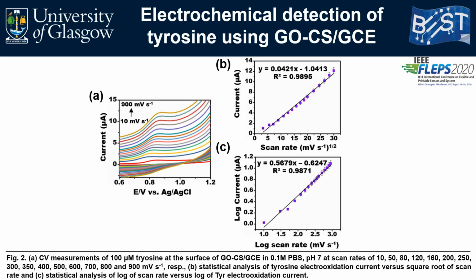As can be seen in Figure 2b, the oxidation peak current has a linear relationship with the square root of the scan rate, suggesting diffusion-controlled reaction kinetics. This electrooxidation mechanism was further confirmed by the linear relationship between the logarithm of the applied scan rates and the logarithm of the measured current, as demonstrated in Figure 2c. The linear plot presented a slope value of 0.5679, further indicating a diffusion-controlled mechanism.